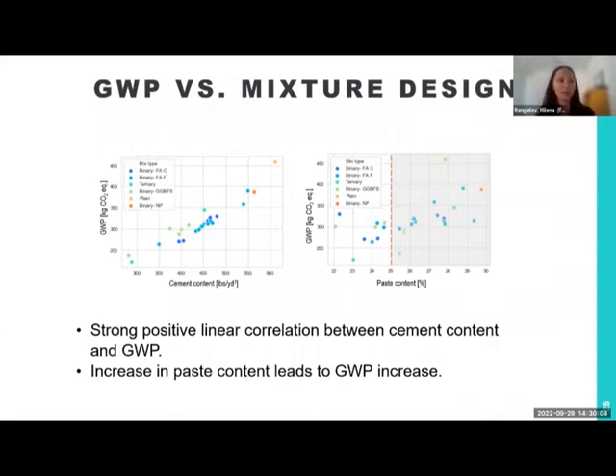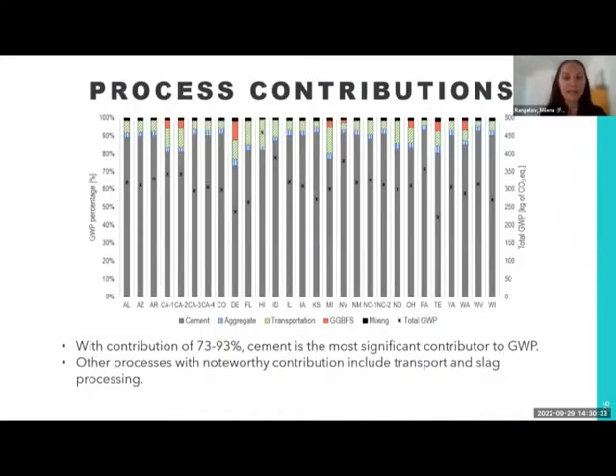On the right-hand side, we can see correlation between cement paste and GWP. It is still positive correlation, but it's not as prominently linear because not all pastes are created the same. So 17 mixes didn't have paste content below the recommended 25%. We have done redesign and recommended some improvements to save in terms of environmental impacts. But before we go there, I can show you process contributions for all of these mixes.